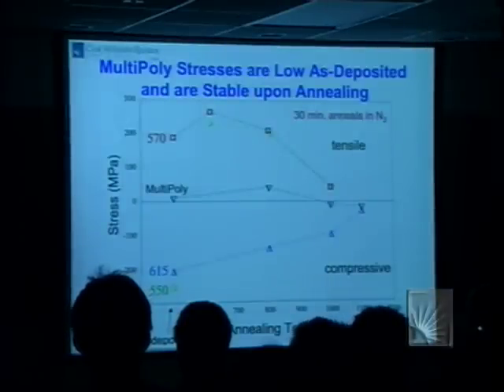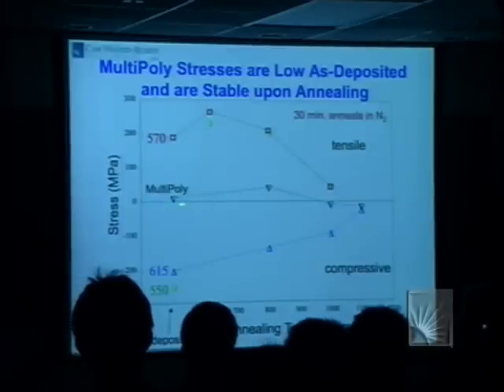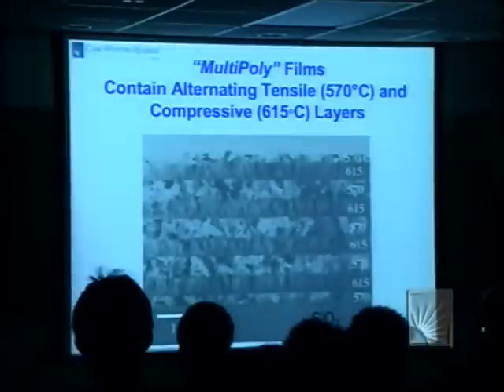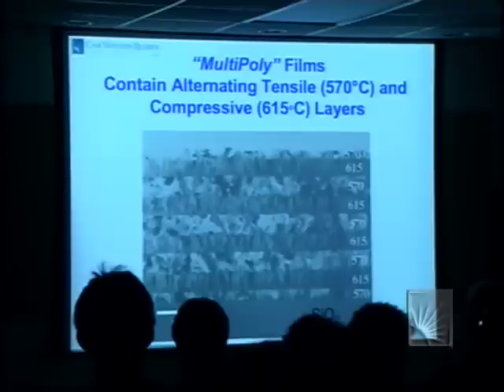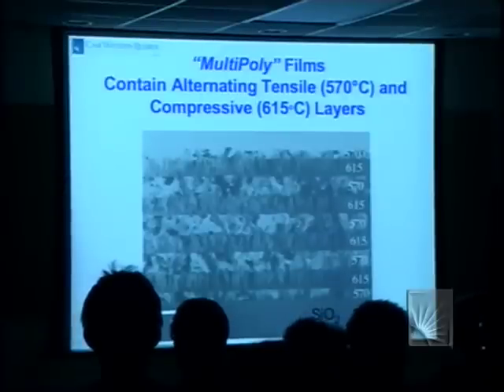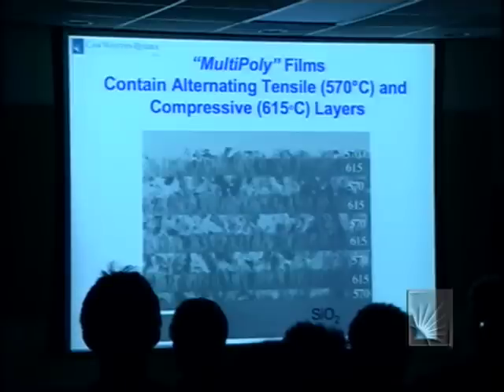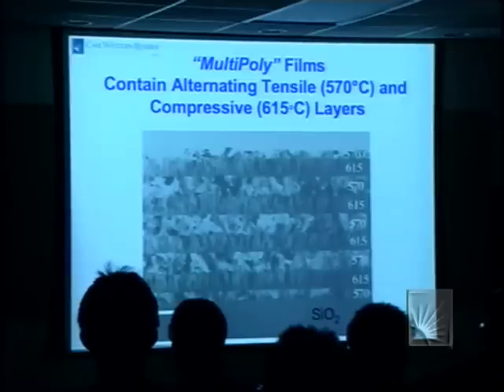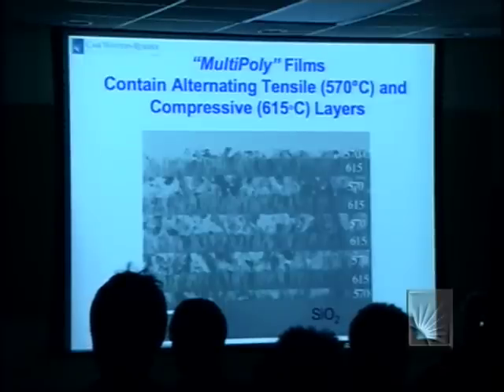And of course, I wouldn't be telling you about it if it didn't work. And so you can, depending on how careful you are, make the as-deposited stresses as close to 0 as you like. And these materials are pretty robust against further annealing. Now, there are many ways to add up positive and negative numbers to come to 0. That's the easy part. I mentioned earlier that there are stress gradients in each of these films. And so if you measure the stress gradients and then adjust and get to 0 in just the right way, you can make films which have 0 residual stresses overall and 0 residual stress gradients.